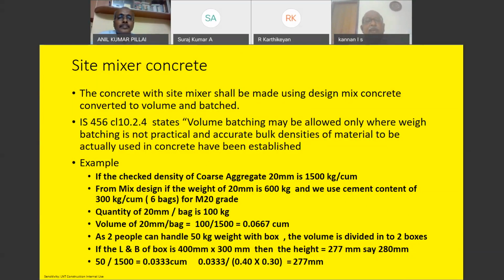Even IS specifies, as per clause 10.2.4, that volume batching may be allowed only when weigh batching is not practical and accurate bulk densities of the materials to be actually used in the concrete have been established. That means when you are able to establish the bulk density of the material, you can very well convert that volume into weight and do it straight away. What you can do is do the design mix by weight.